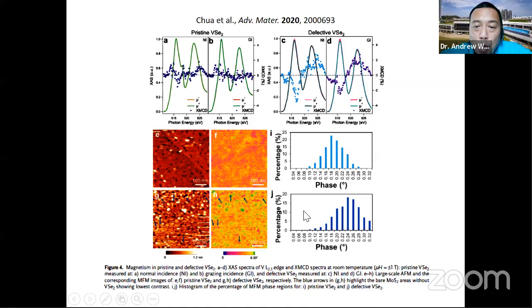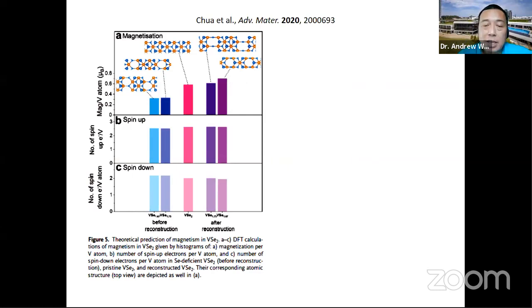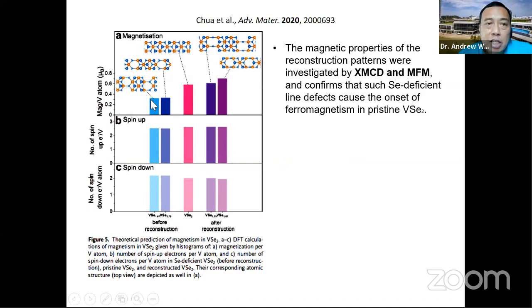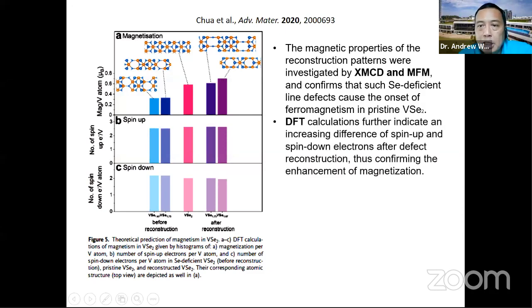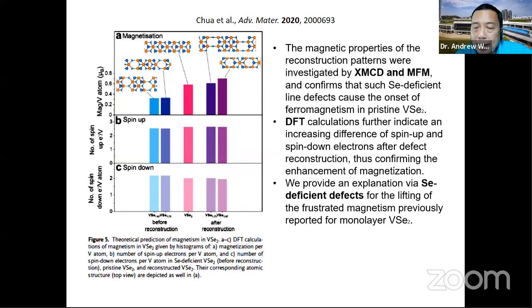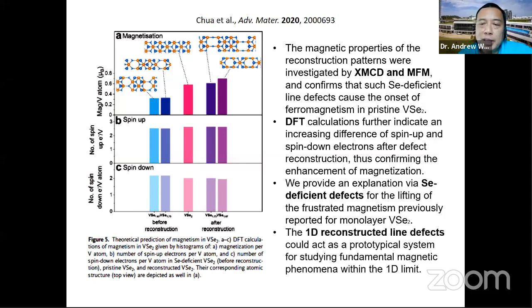So clearly, the more defective vanadium diselenide shows a phase shift, so it shows magnetism. Okay, so we have magnetic measurements on this material showing magnetism indeed, and these are the DFT calculations that show that we have this structure on the right with the 8 member rings. You can actually get an increase in the magnetism per atom. So we conclude in this paper, and we hope we have resolved the controversy, that selenium deficient defects are responsible for lifting the frustrated magnetism previously reported in monolayer vanadium diselenide. So that's an interesting model, and that hopefully gives some insight into 2D TMD magnetism.